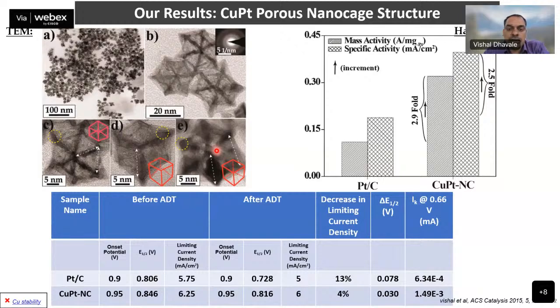So these open architecture structures, when we utilize them for the overall catalyst, have been utilized for alkaline conditions. As the copper was there, to avoid the leaching out of the copper, we tested in alkaline condition, and you can see the 2.9 fold improvement in the mass activity, as well as specifically, you can see 2.5 fold improvement compared to the state of the art catalyst. So taking advantage of all these things, we have gone for certain further analysis of this material. You can see over here listed in this table. The stability also you can see in this table, before and after the durability test. Hence, it can be seen that the onset potential, the thermodynamic potential, and the kinetic behavior are better in case of the nanocage structure.